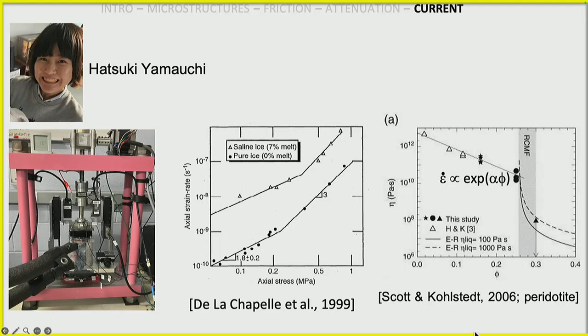And the only previous study on ice plus saline was this one from 1999, where they found this distinct softening, this is strain rate, when you had 7% melt. Well, she is looking at less melt, quite a bit more melt, and the curves are fitting beautifully with the previous data. And so she is well on her way. Again, with this sort of two mechanism little pivot in it. It's looking really nice, and she'll be able to take from all these different melt fraction samples, go back over to this plot and start coming up with this linear relationship, which we refer to as alpha.